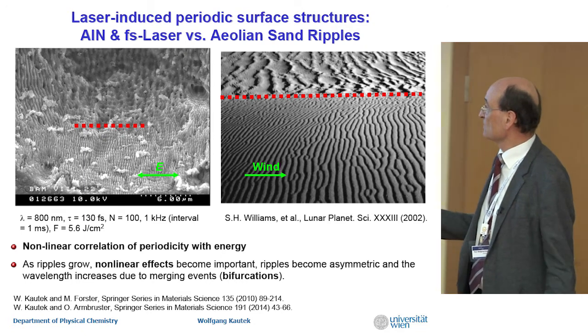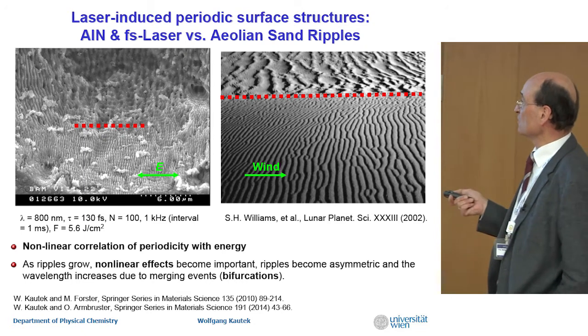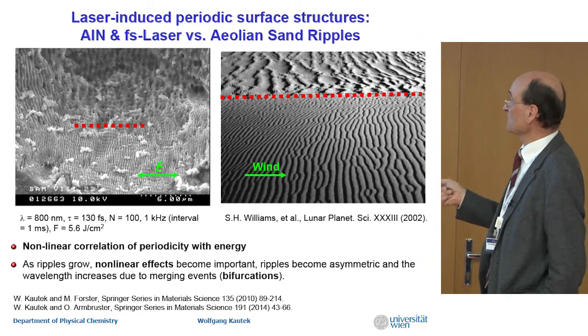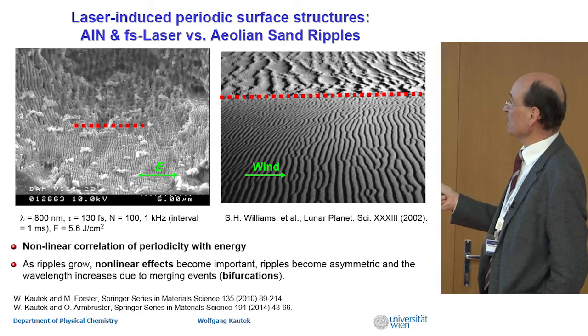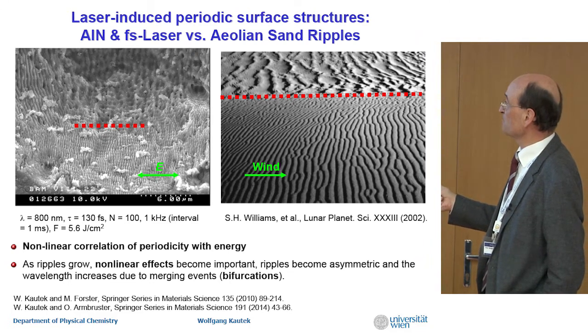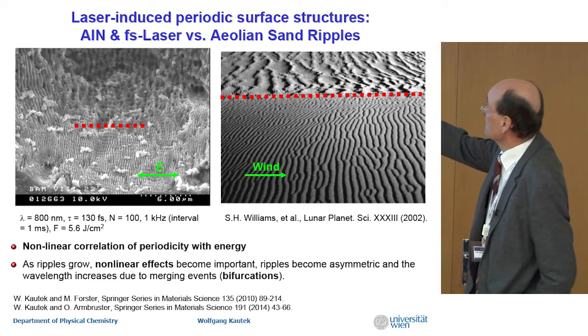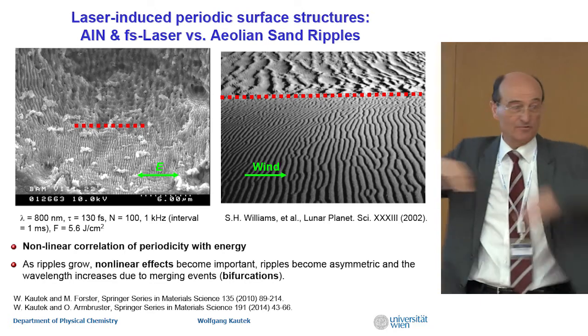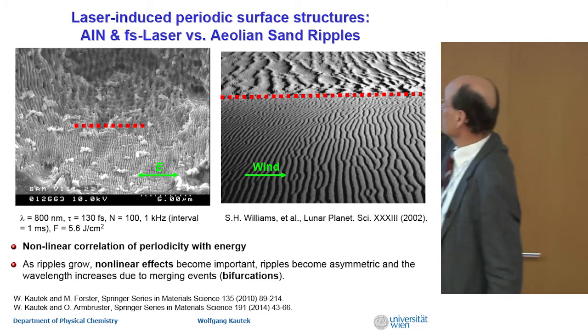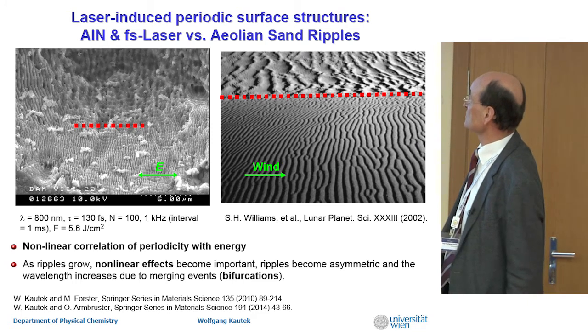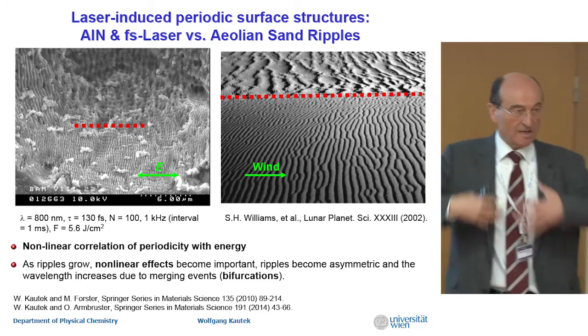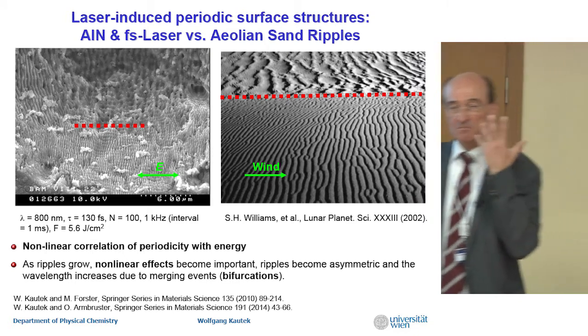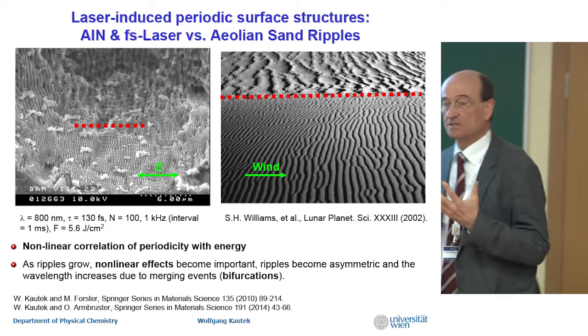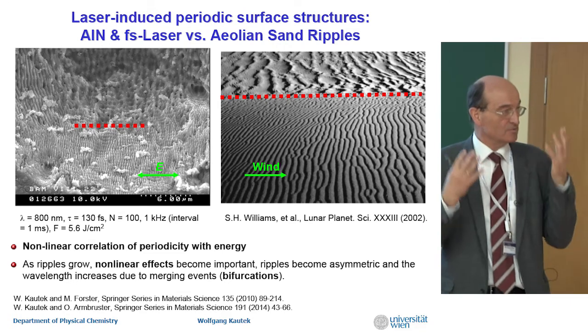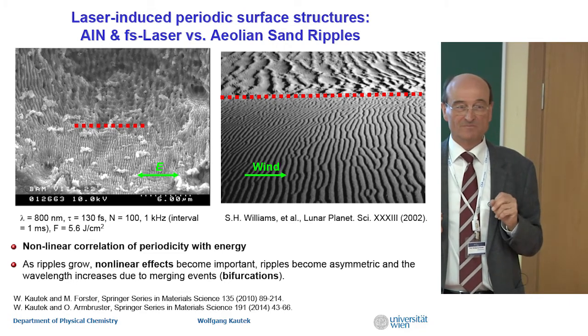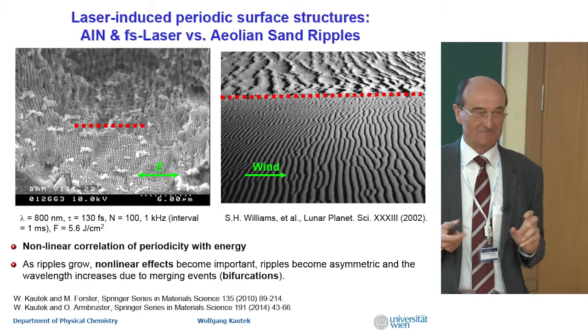And as the ripples grow, nonlinear effects become important. And we also have a phenomenon which you could call bifurcation. So that's not an interference pattern. This is typical for self-organization, and you find that also there. How can you trigger a solid material to form these ripples? You have to destabilize it somehow.